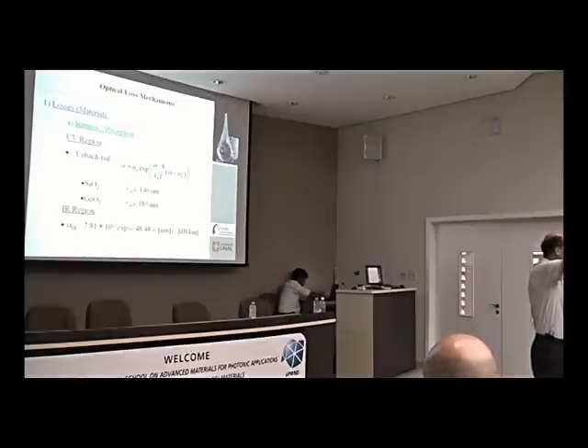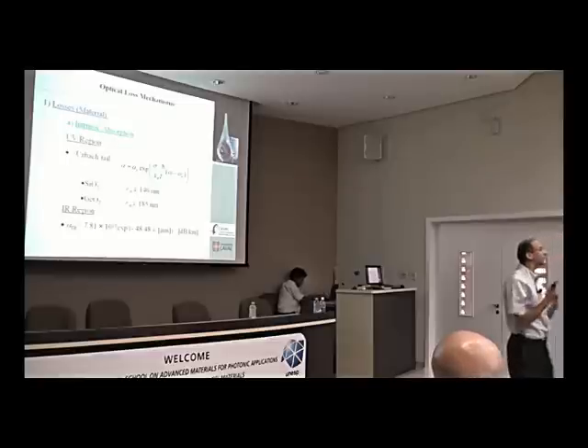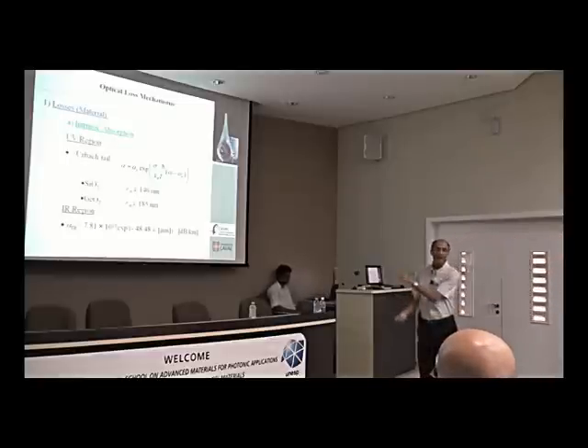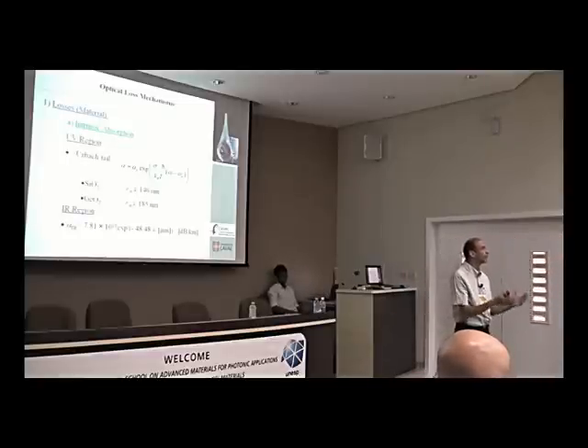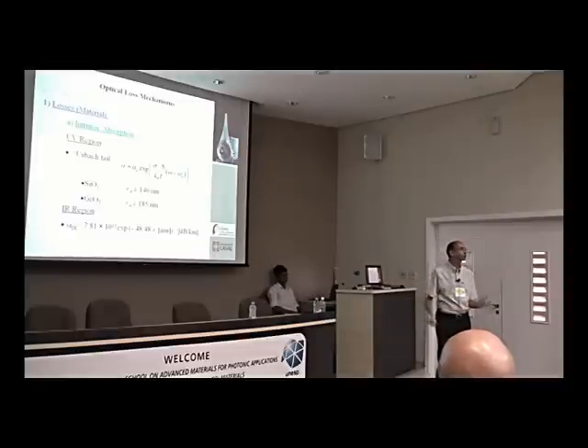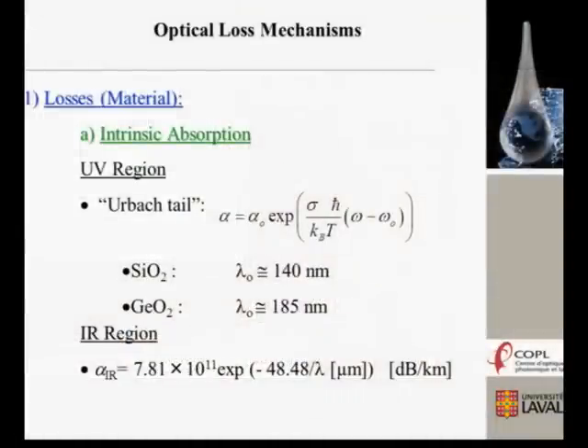Remember these two levels, and this is so important for us. Depending on the material we are using, and I give an example here, for silica we are using 140 nanometers, and for germanium it's 185. For phosphate, it's 220. For fluoride, it's 240, etc. Depending on the starting material, this is what I said in the beginning. The component of the material that you are using is so important, and it's the parameter that you will use depending on the application that you are using it for.